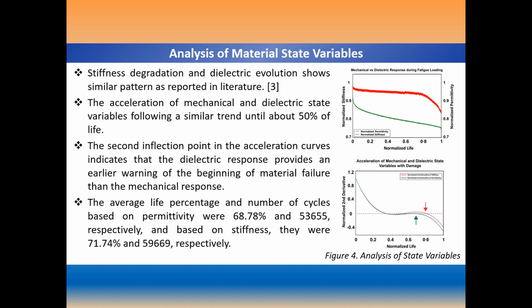During fatigue, stiffness degrades, which has a similar evolution pattern as the dielectric permittivity response. However, an accelerated decrease of permittivity is noticed at around 75% of life, predicting the failure earlier than the stiffness degradation phenomena. The same is evident in the acceleration of the state variables, where the second inflection point in the dielectric state variable acceleration curve is at about 68% of life, and the respective point for acceleration in the mechanical response curve is at about 72% of life. Thus, the dielectric response is more effective in providing an earlier warning of the beginning of the failure of the material.